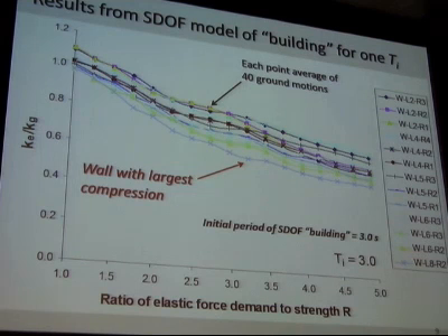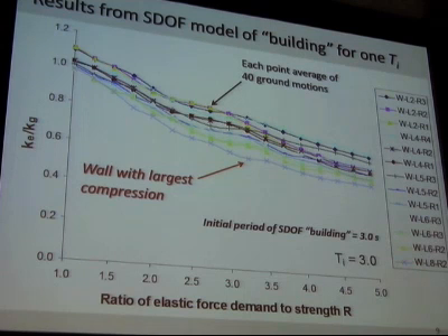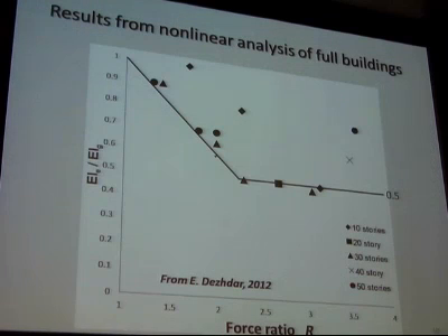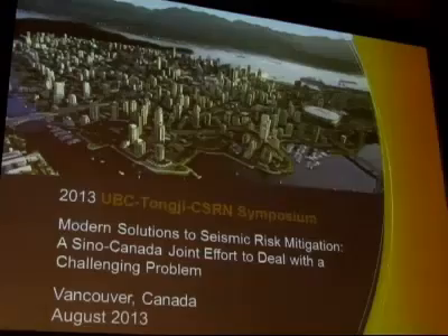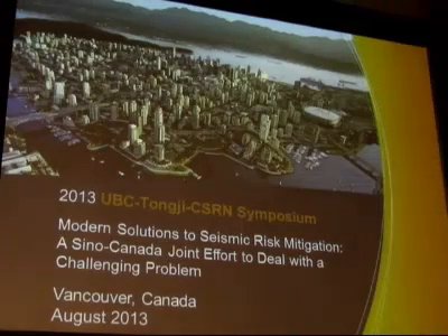So in other words, what we have in the code right now has it exactly wrong or exactly backwards. Actually, a wall with a high axial compression will generally have a lower effective stiffness because it'll dissipate very little energy. It's like a rocking mechanism. Okay, and looking at really the strength of the wall as a ratio of the elastic demand is the right way to go. And here are some results from Dezhdar, from nonlinear analysis of essentially full buildings. And what you see is that instead of relating it to the axial compression, what we need to do is relate it to the strength.